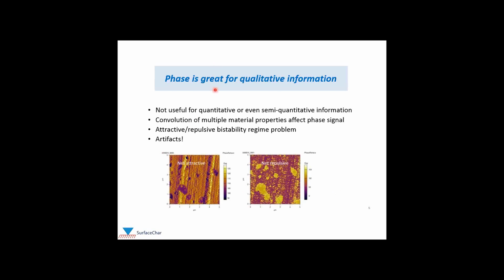So let's start with phase. I'll come right out and say it, not very useful for quantitative or semi-quantitative information. Phase is great as a qualitative tool. But the problem for mechanical measurements is several-fold. The first problem is that there's a convolution of multiple material properties that affect the phase shift, the phase signal that we're mapping, which means that you cannot really assign the phase contrast to an individual mechanical property like stiffness or adhesion, for example, because it's really a convolution of everything that's causing the phase shift.